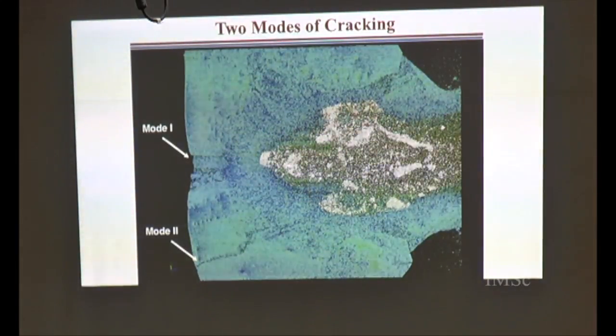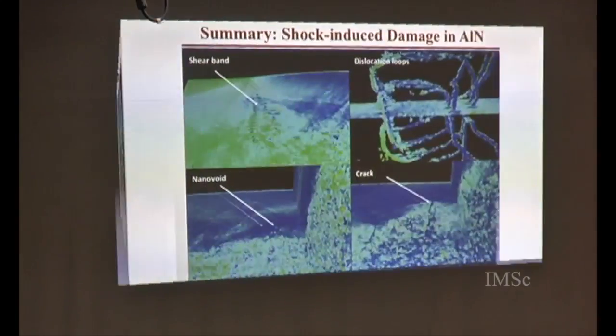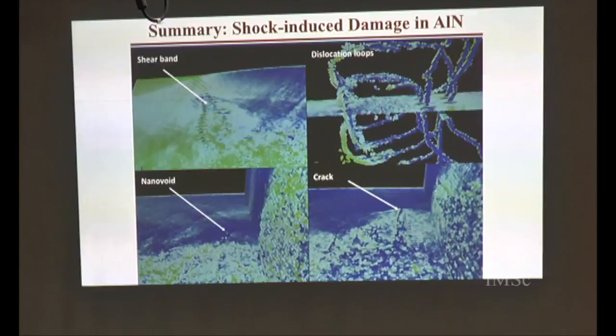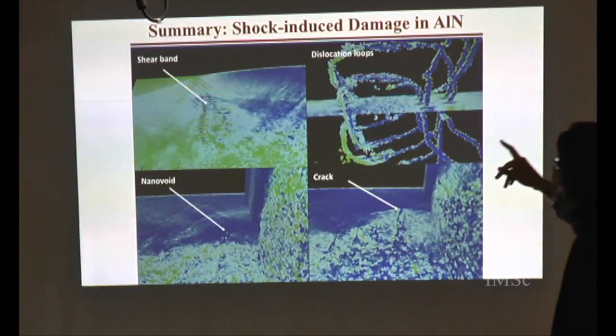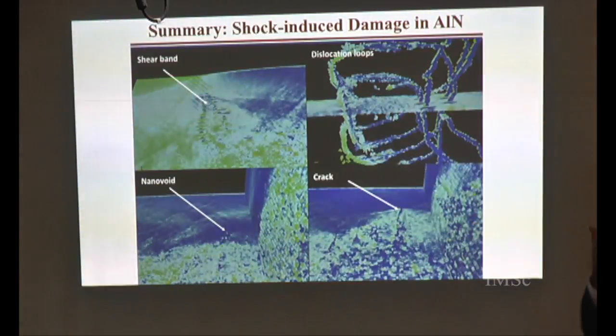So to summarize this part, in this impact damage simulation on aluminum nitride, I think the key message is you see a structural phase transformation from Wurtzite to rock salt. At the Wurtzite rock salt interface, there is large lattice mismatch, and when the stress wave reflected from the back end of the sample hits this interface, that's where the damage begins. And the damage is in the form of shear band, dislocation loops, nanovoids, cracks, sort of very rich.